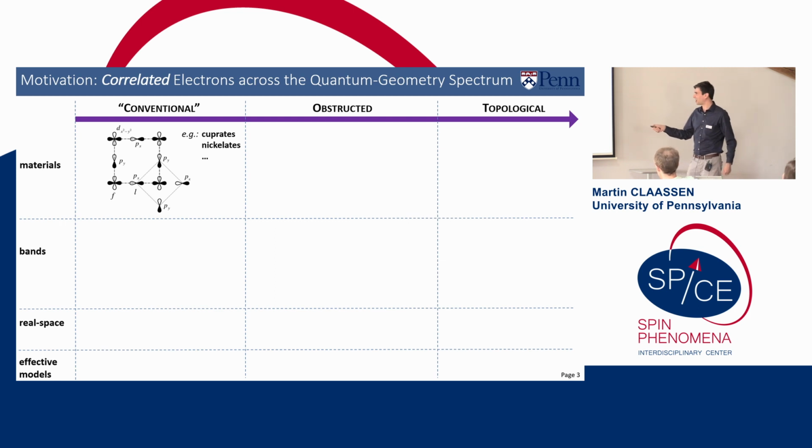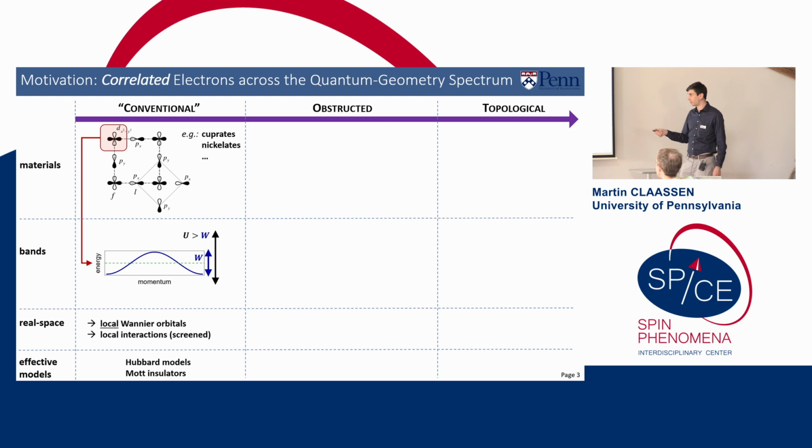So here is an example of a copper-oxygen plane in a cuprate. That might, for instance, be undoped lanthanum copper oxide as the very simple toy example. At low energies, we understand the system very, very well in terms of essentially strong electronic interactions for the d_{x^2-y^2} orbitals of copper. So to very good approximation, low energy physics is captured via a single band Hubbard model where you have a single band with a bandwidth that is much less than the electronic interaction, such that at low energies, we form a Mott insulator that then does very interesting things when we start adding or removing carriers.